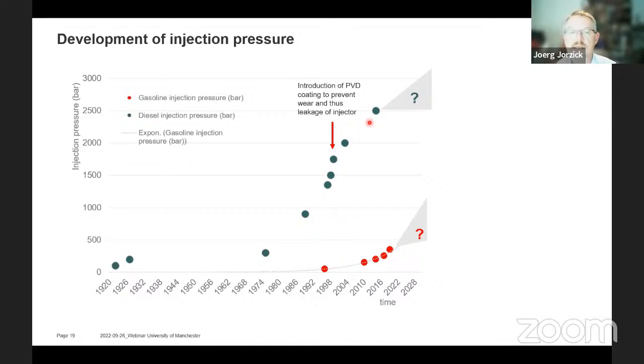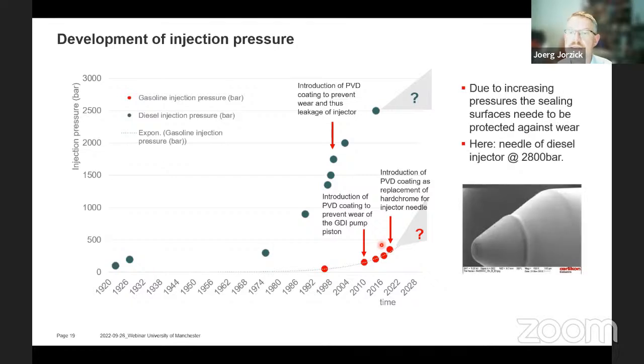And the same trend basically can also be observed for the gasoline injection. Here we saw that for the pump, around 200 bars, when the 200 bar system came up, that the pump piston needed a coating because it was wearing, and moving further up with the pressure as the development was ongoing, we also saw that the needles, so that means the sealing area of the injector, also needed a coating. And here's some example from a diesel injector needle, how it looks like. So here you see this typical wear step, which is happening if the coating is not present. And here you see that it is this 2,800 bar from an actual needle.